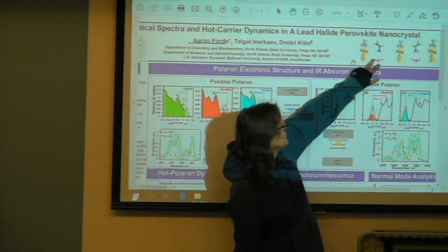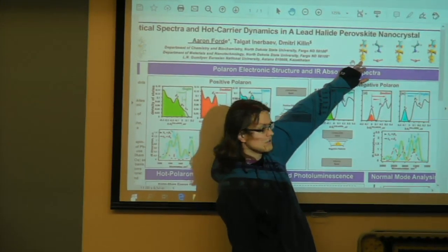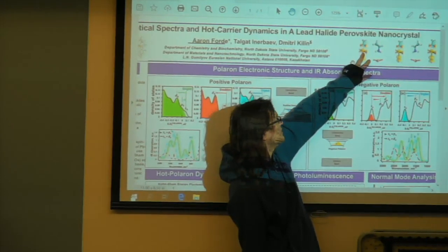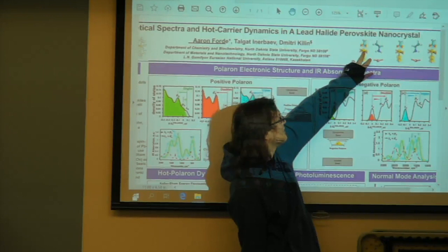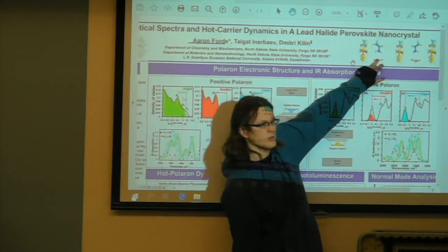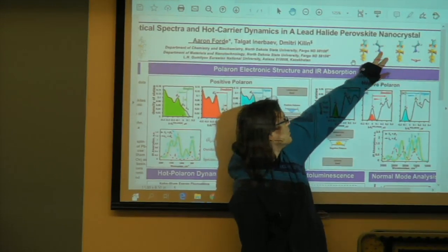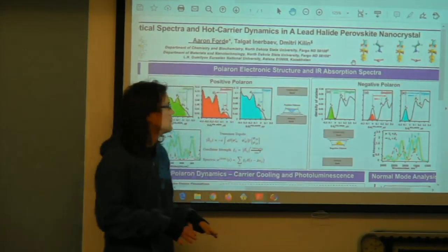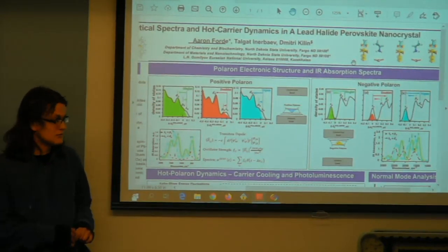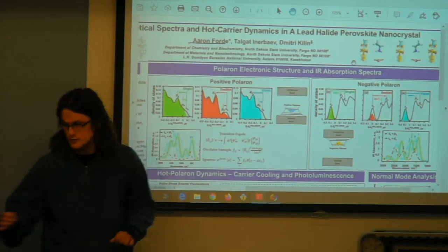If you consider the surface of the perovskite, these are carboxylates, which form chemical bonds, illustrated with the electron density, whereas the ammoniums coordinate to the surface, but they don't directly bond. So they wouldn't provide vibrational modes to couple.